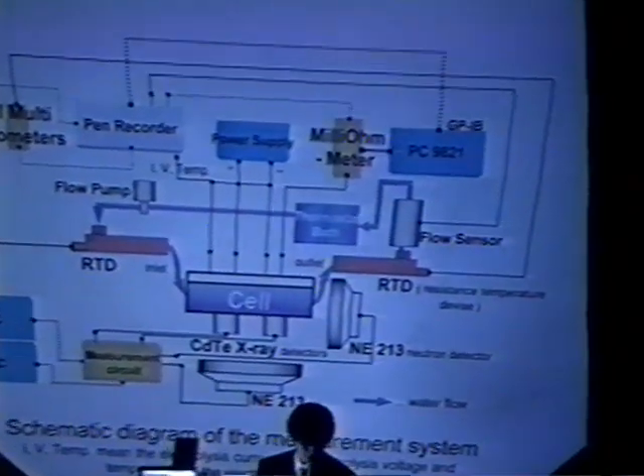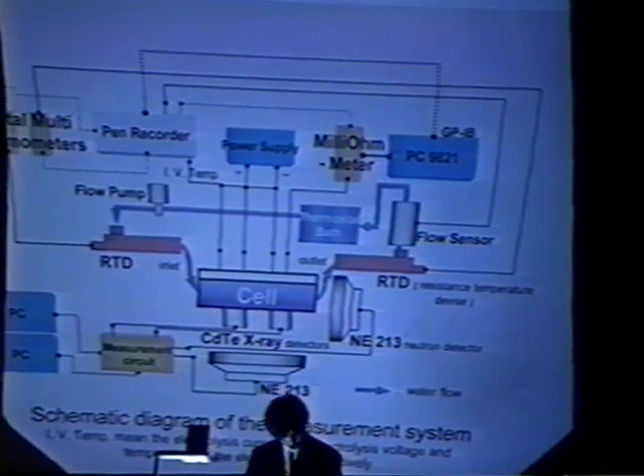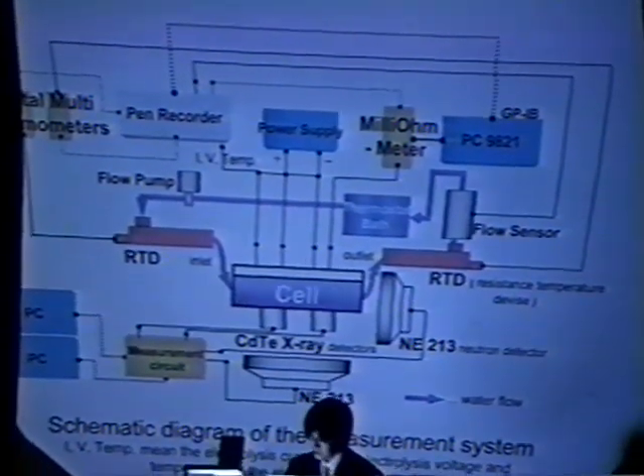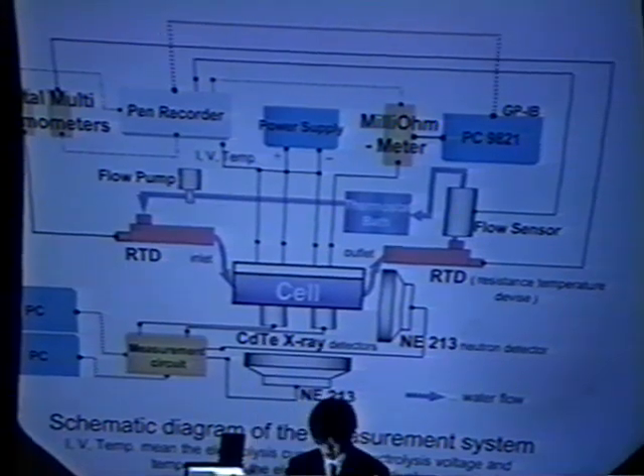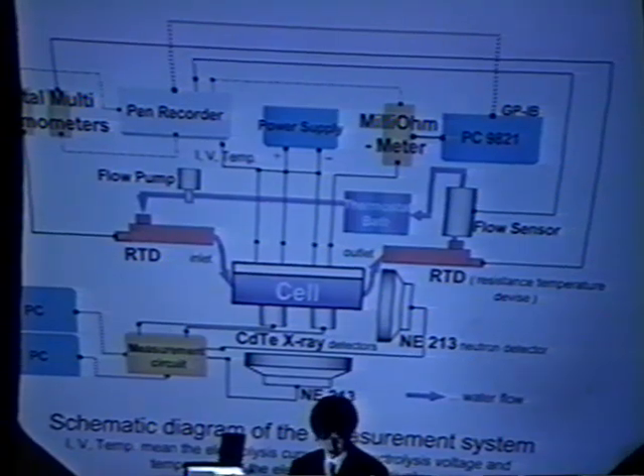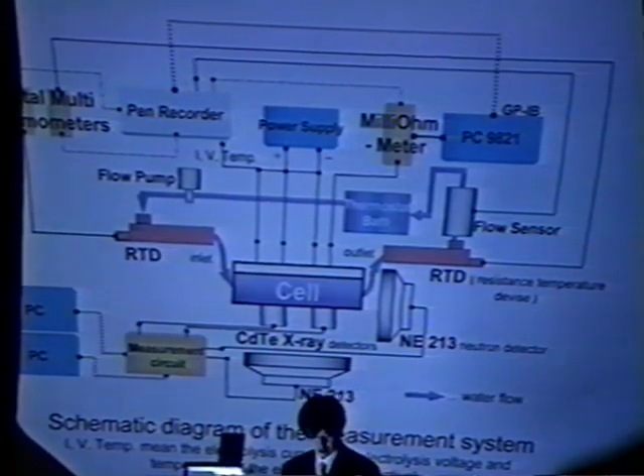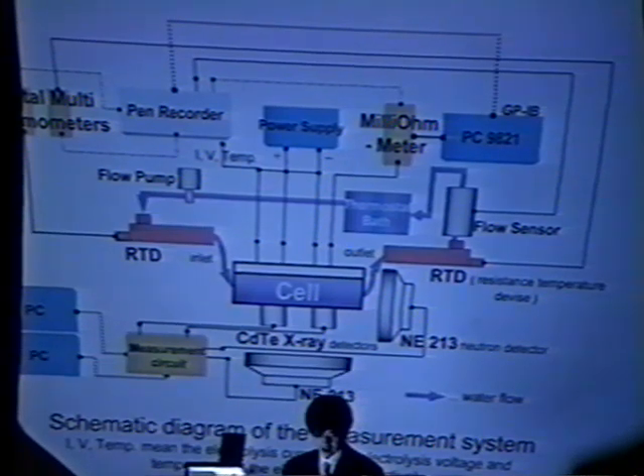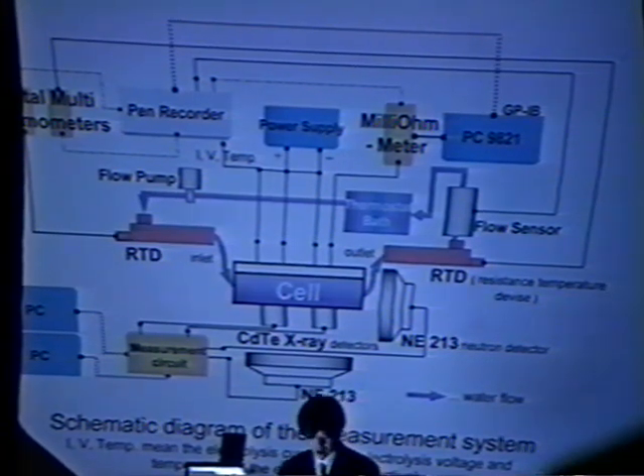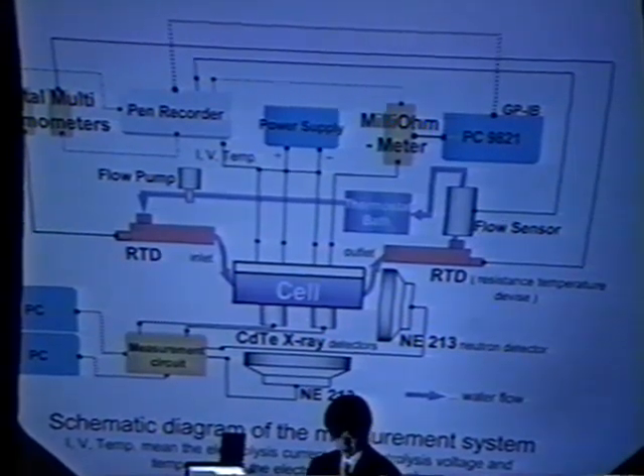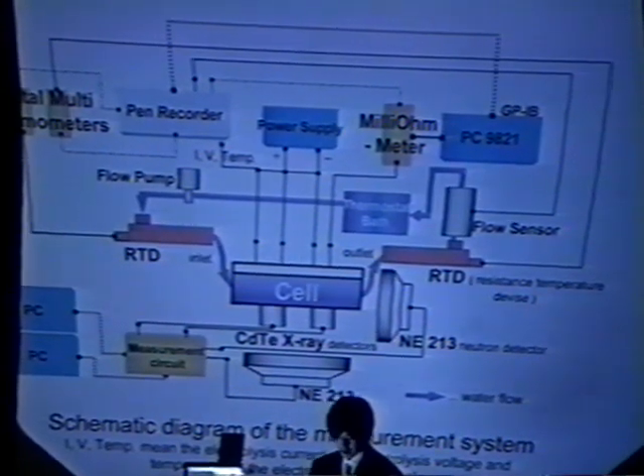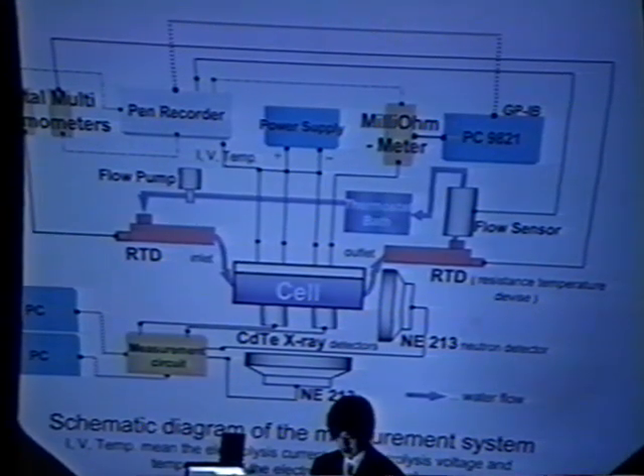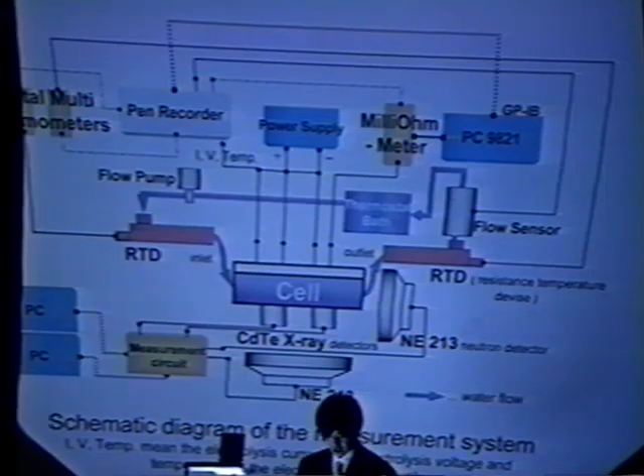This is a schematic diagram of the measurement system. Two X-ray detectors and two neutron detectors were used for nuclear product measurements. As we use a two-detector system, the reliability of the measurement data was improved by seeing simultaneously occurring events in both detectors. For example, if one of the detectors detected an increase of signals and the other detector did not, we considered it was noise or statistical fluctuation.